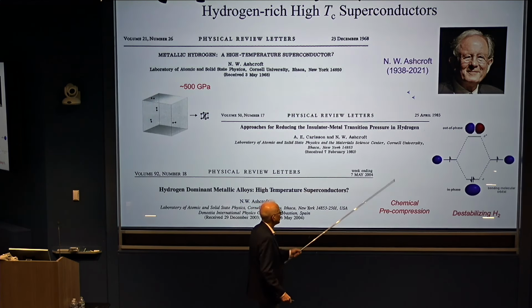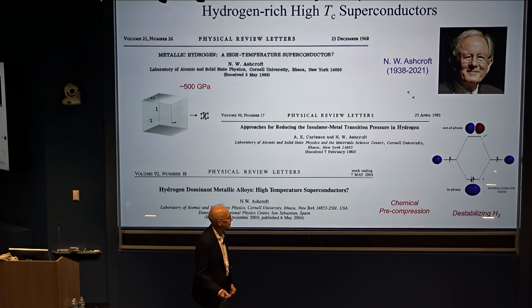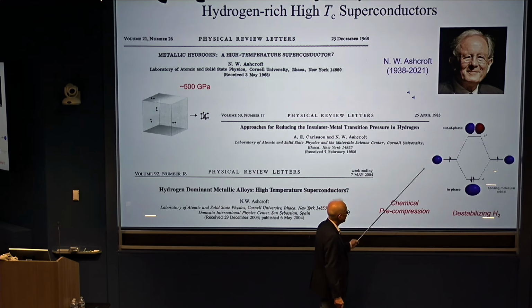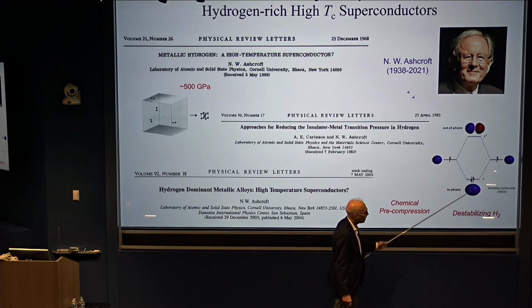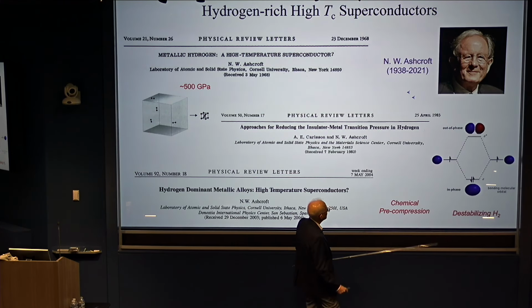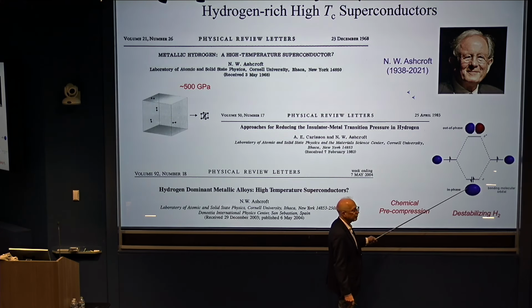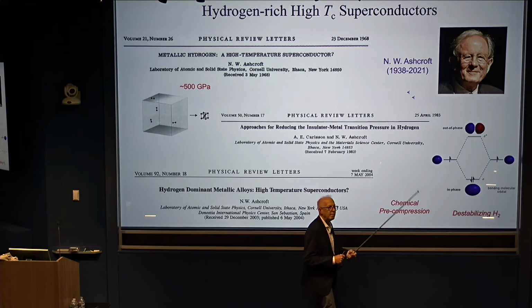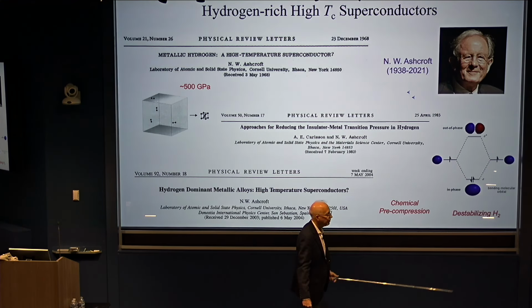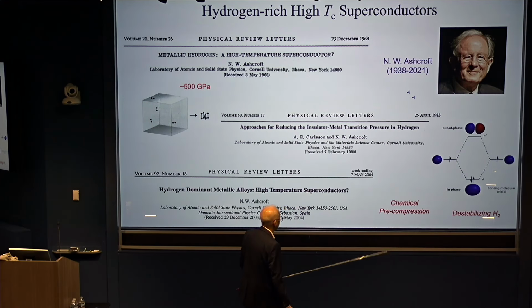And coming back to the work of Neil Ashcroft and his idea that you'd have superconductivity in metallic hydrogen, he suggested quite early on various ways to reduce that transition pressure. And he suggested going back to looking at basic molecular orbital theory, kind of along the lines of what I mentioned for Heitler, London, and Pauling, if we could simply take electrons from the bonding orbitals and put them in the antibonding orbitals in some fashion, we could destabilize this very strong molecular bond, and that might facilitate the formation of a monatomic solid, or liquid, with these interesting properties.